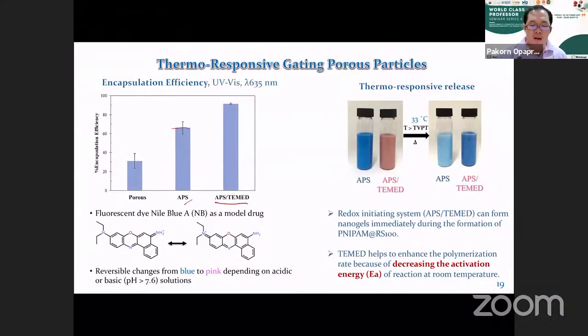After that, we measured the encapsulation efficiency. We also tested the thermoresponsive behavior of the materials by measuring the amount of the indicator that is released from the materials at the temperature of 33 degrees Celsius as the borderline. So we lower the temperature below 33 degrees Celsius or raise it above 33 degrees Celsius to trigger the close and open mechanism of these materials. And you can see the color here indicates how much of the fluorescent dye, the indicator, comes out from the materials.